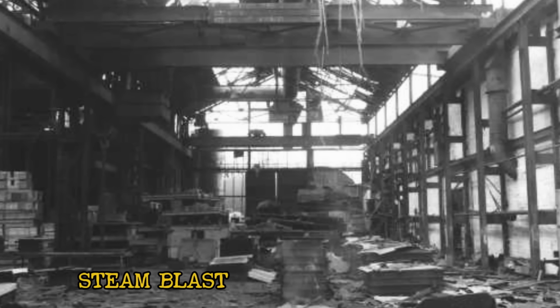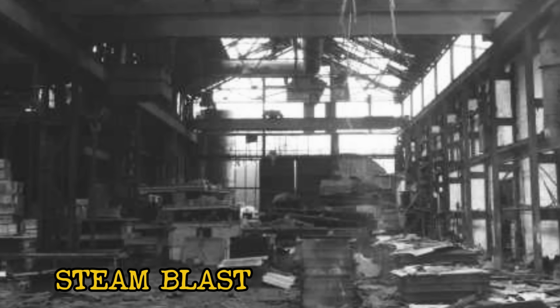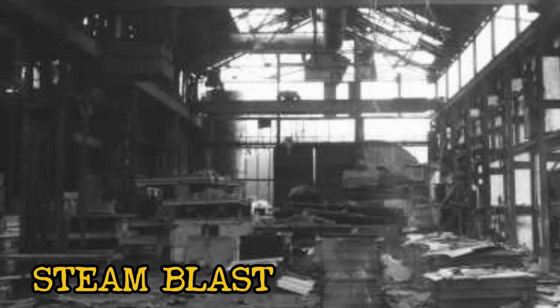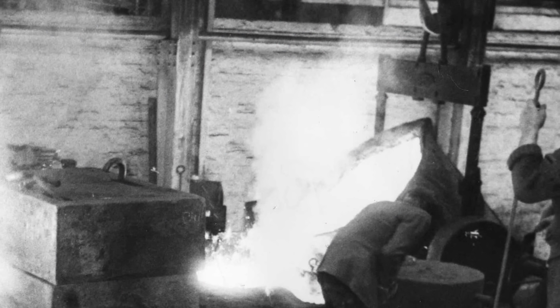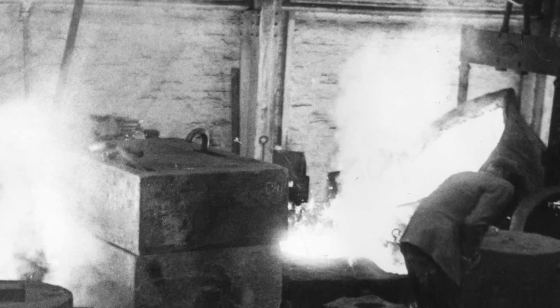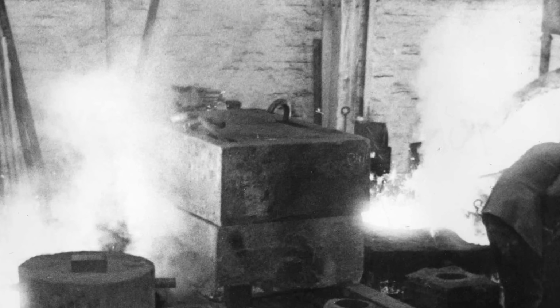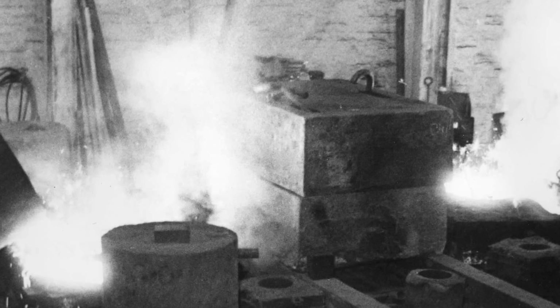Expansion, 1,671 to 1 in milliseconds, confined beneath a layer of liquid metal. The pressure has nowhere to go but out. The explosion tears through the foundry, a steam blast so violent it shatters the ladle, fragments the trough, and aerosolizes the molten steel into a spray of white-hot droplets. Streams of burning metal pour outward in every direction, like water from a burst pipe, exactly as the newspapers will describe it. Liquid fire showering down on the men working the cupola, the men moving molds, the men who happened to be in the wrong place when physics turned savage.